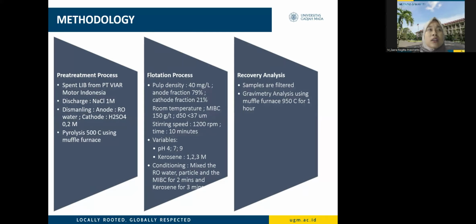0.2 molar sulfuric acid. The final stage is the pyrolysis using a muffle furnace for 2 hours at a temperature of 500 degrees to remove the binder attached to the material. To determine the differences in material before and after pretreatment, contact angle analysis and Raman spectrophotometry were carried out.